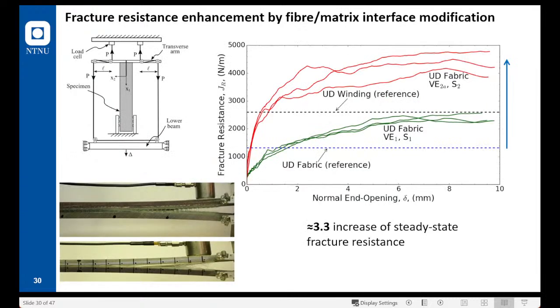Based on these results, we have gone back to the lab, and through chemical modifications at the fiber matrix level, we were able to modify the fracture energy corresponding to the bridging zone, and we were able to increase the fracture resistance of the composite by 3 times. So from the modeling, we have gone to the experiments, modified the material, and we have managed to increase the fracture resistance 3 times.